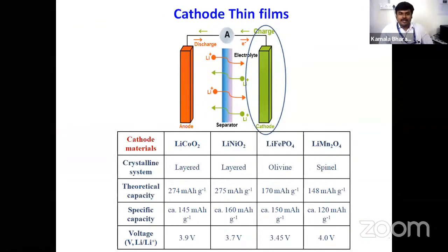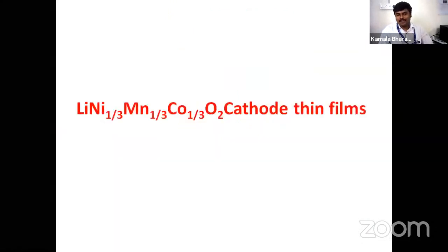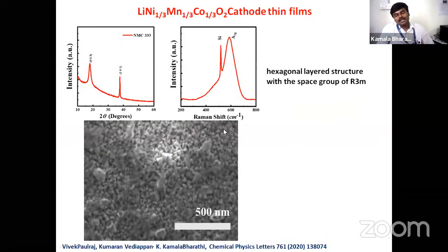So I will first get into the cathode thin films. We have been working on several materials, but today I'm going to tell only one or two materials in each category. So first I will talk about the lithium nickel manganese cobalt oxide cathode films. So we fabricate these films using sputtering, and this is the XRD pattern, and this is the Raman spectra of this thin film fabricated at 600 degrees Celsius.